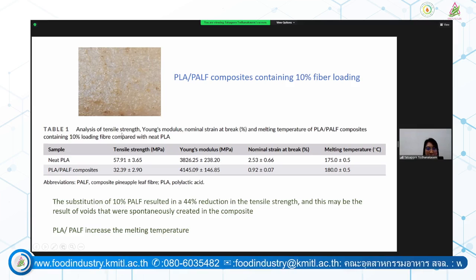Okay, so when we look at the mechanical properties of the material that we made, based on the tensile strength, Young's modulus, strain at break, and melting temperature, comparing with the one that contains no PALF, or the pineapple leaf fiber. What we found here is that the tensile strength cannot be comparable with the neat PLA. This might be caused by the fiber mixed with the PLA creating some voids or porosity inside, so the tensile strength is reduced. Somehow this can be improved in the future by doing better pre-treatment of the pineapple leaf fiber to minimize the voids or the porosity of the material.